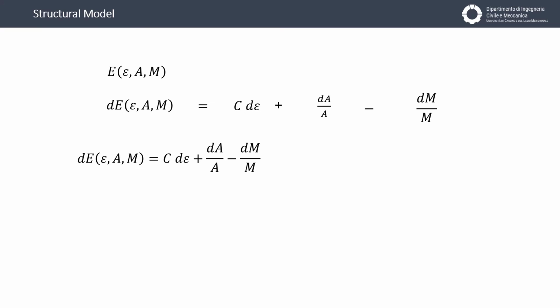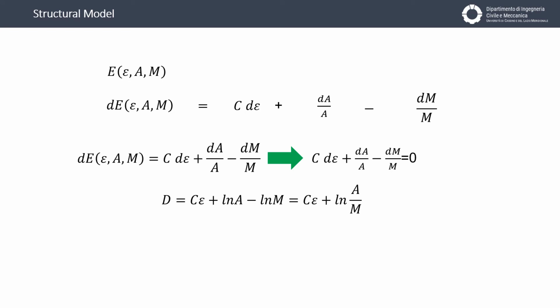The equilibrium takes place when this differential is equal to 0, like this. And integrating this equation, you can see that the formulation is very, very easy. A constant D is equal to the constant C, which multiplied the deformation, plus the logarithm of austenite on the martensite. Taking into account that the summation of quantity of austenite and martensite is equal to 1, you can calculate the quantity of martensite like this and the quantity of austenite like this. These are the equations which calculate the quantity of martensite and austenite during a deformation process characterized by an epsilon of deformation level.